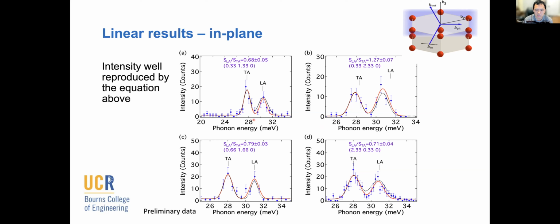Here we're showing the fitted experimental results in red line on top of this dashed calculated intensity. You see that the TA and LA are supposed to have a very similar intensity at many Brillouin zones, and our calculation actually agrees almost perfectly. And we thought, oh, it's interesting, it's a non-result.